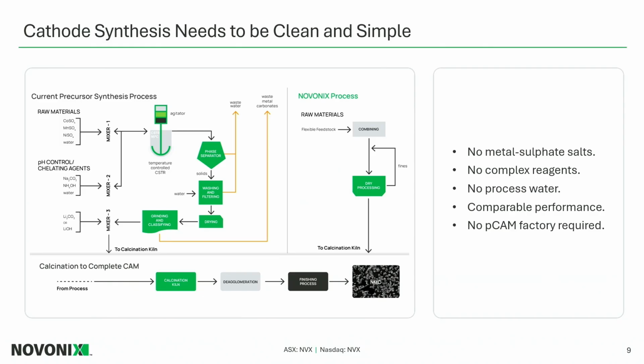So I'm illustrating here a comparison flow sheet from the conventional PCAM synthesis, which I labeled the current precursor synthesis process. It's co-precipitation. Typically, you take metal sulfate salts, react them in a continuous stirred tank reactor at elevated temperature, add in different reagents like sodium carbonate and ammonium hydroxide for pH control, and then you precipitate out these beautiful, highly engineered precursor powders. From there, there's a whole bunch of other unit operations, which require energy, require people to run the equipment, and each step generates more and more waste. There's phase separation, washing and grinding, et cetera, et cetera.